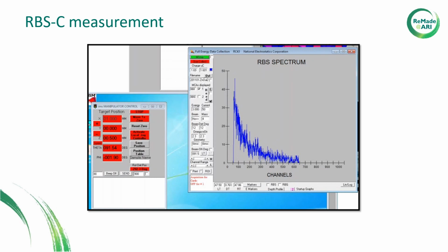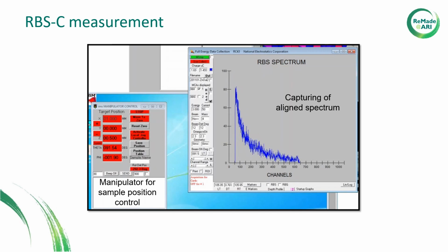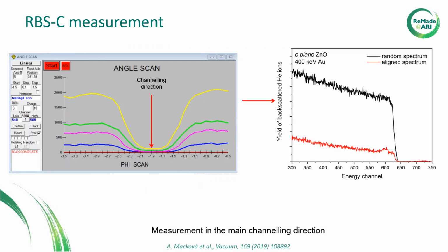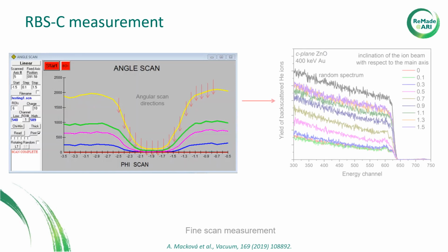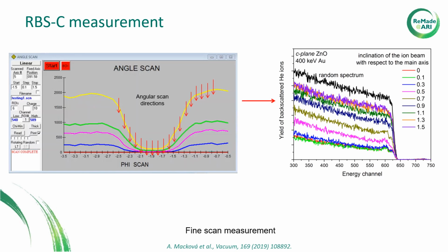When the channeling coordinates are known, we rotate the crystal to align the ion beam with the channeling direction, and we capture the RBS aligned spectrum. The channeling spectra can be captured only in the main channeling direction, as is usually done for analysis of relative crystal disorder and investigation of overall crystal quality. However, we can also perform an angular scan measurement, when the crystal is slightly rotated along one of the main axes and multiple spectra are recorded, a fine scan. This is usually applied for the study of lattice channel deformation or dopant positioning.